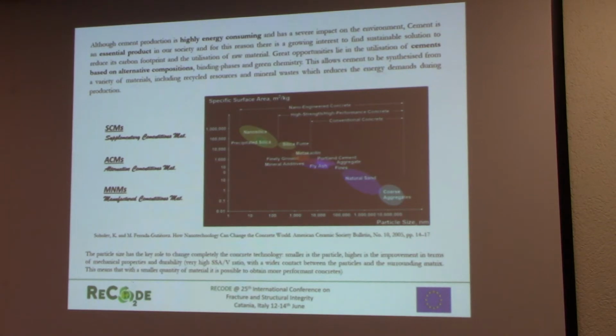The main value of these materials is the size. The nanosizes play a very crucial role in the innovation of concrete technology. As you can see, if we move toward the nanometer particle size, the specific surface area increases dramatically. And this means that the particle possesses a very high specific surface area to volume ratio. This means that there is a wider contact between the particles and the surrounding matrix, and this means that with a smaller quantity of materials we are able to obtain very performing cementitious materials.